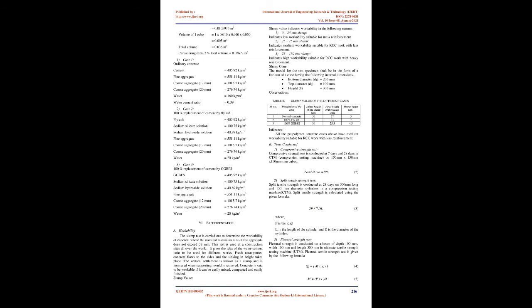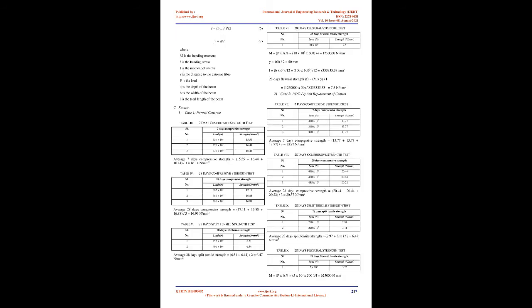A sodium silicate/water glass alone can't be utilized as an activator to start pozzolanic reactions. NaOH and Na2SiO3 are the most regular alkali activators utilized in the geopolymer concrete production. Commercially, sodium silicates can be found in various grades and states, for example, powder forms/liquid forms. However, liquid form has more tendency to start reaction. It is found from the survey that Na2SiO3 having SiO2 to Na2O mass ratio of 2.0 mixed with NaOH activator 24 hours preceding use offers better outcomes.